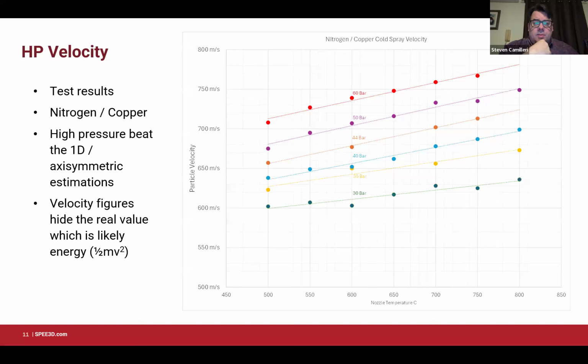So I've included this as a bit of a reference for those of you that are interested in not just how our nozzle works, but how cold spray nozzles in general work. On the bottom axis here is the stagnation temperature, which is usually controllable on a cold spray system as it is on ours. And I've put a separate line for each system pressure, so each line is a line of constant pressure. What you see here is the HiWatch measured actual particle velocity. This isn't inferred or calculated. This is the actual data measured in the middle of the particle grouping.